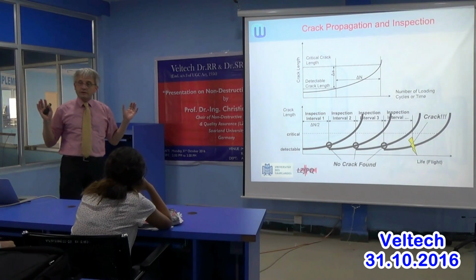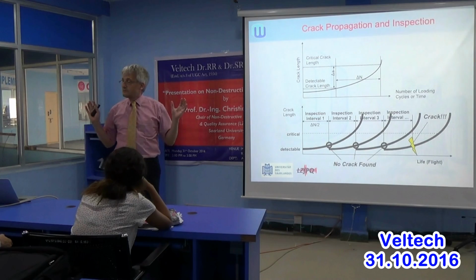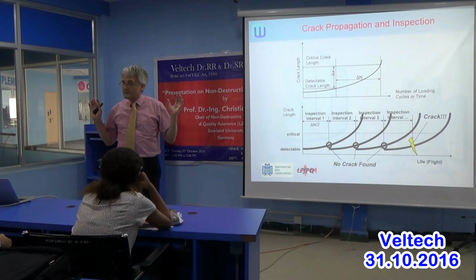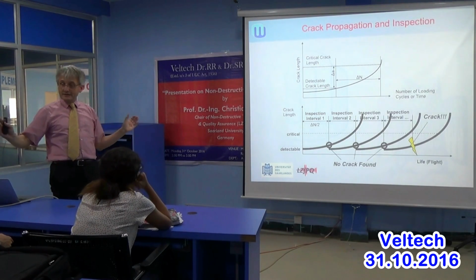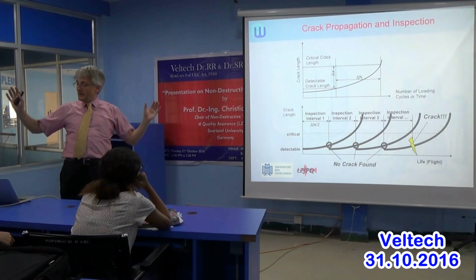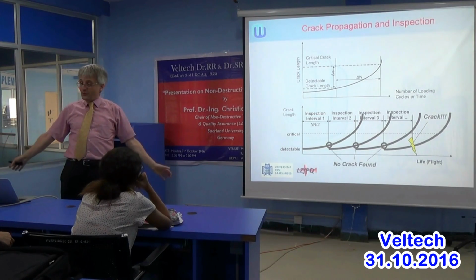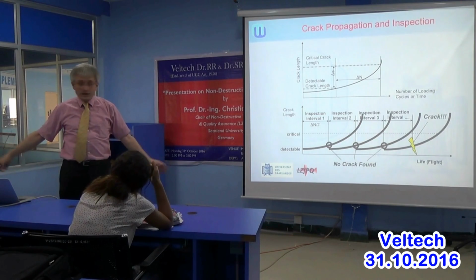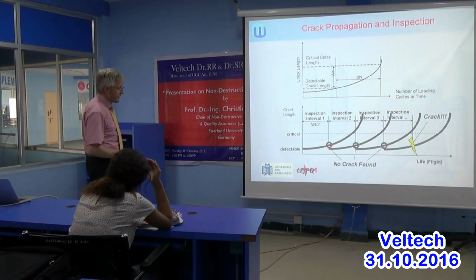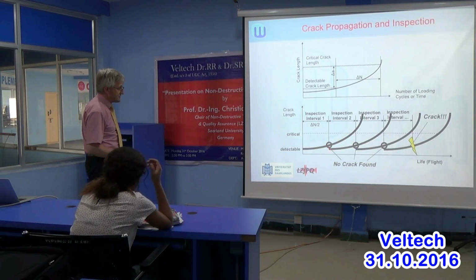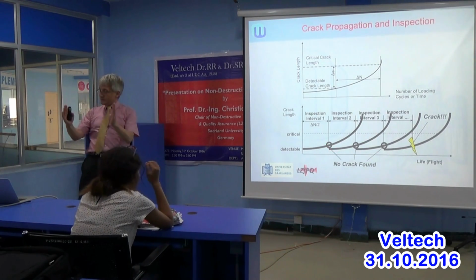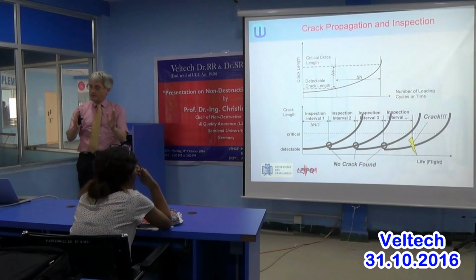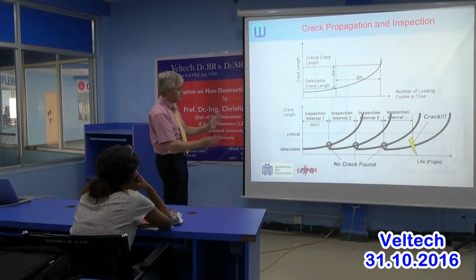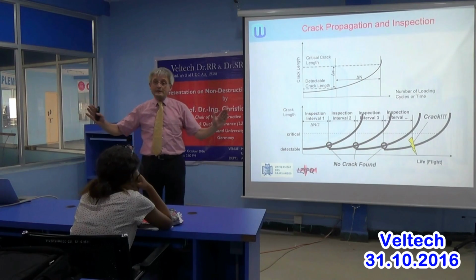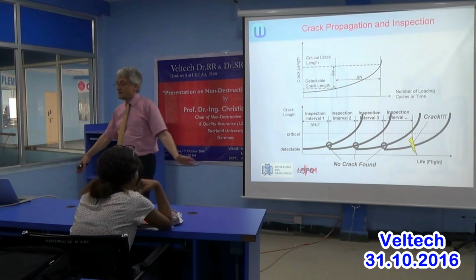So what does that mean? We don't see a crack. The crack is still not detectable. So it means our assumptions we had before are still valid. So we take again the same. We say, okay, the crack obviously has not moved as much like here, so we still can start from here. Let's look again after a certain interval if something happens. And if again nothing happens, we continue, and we do that all the time until we find a crack.